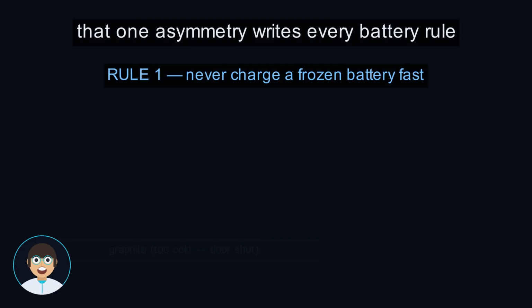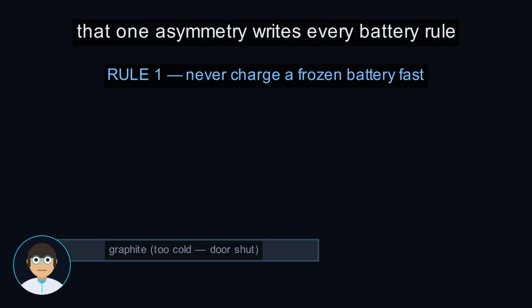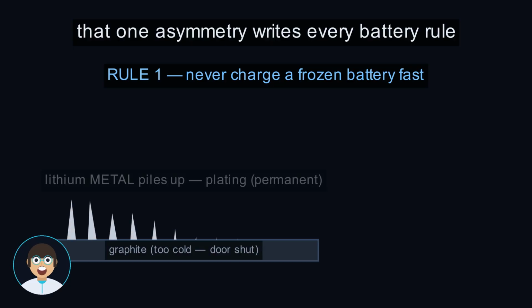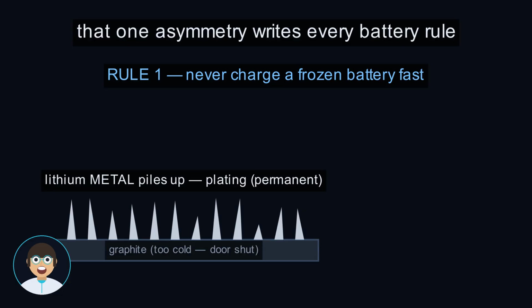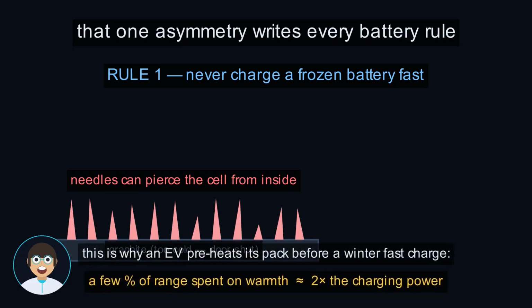Rule 1, never charge a frozen battery fast. Draining it cold is merely slow. But when charging cold, lithium arrives at a door that will not open and piles up outside as raw metal. Plating, it is permanent, and it can grow needles that pierce the cell from inside. This is exactly why an EV heats its own battery on the way to a winter fast charger. Spending a few percent of range on warmth nearly doubles the charging power waiting at the plug.